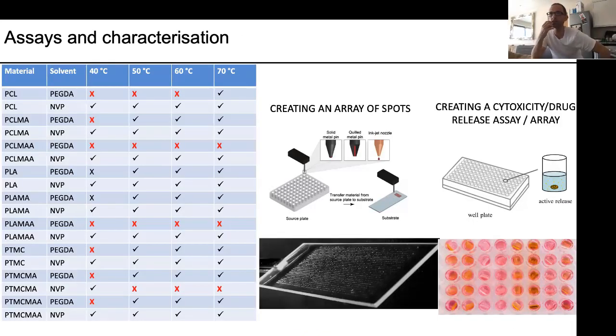We took materials that we didn't really know whether they would be printable or not. We were really interested in biodegradable, implantable materials that were 3D printable, and so we designed a material synthesis program where we created these oligomers that were biodegradable, and we coupled them with various different solvents, in this case PEGDA and NVP, again, blended them and asked the question, are they printable or not? And a priori, we didn't know that, and after our printability assessment, we were able to identify mixtures of these materials that would eventually end up to be printable.